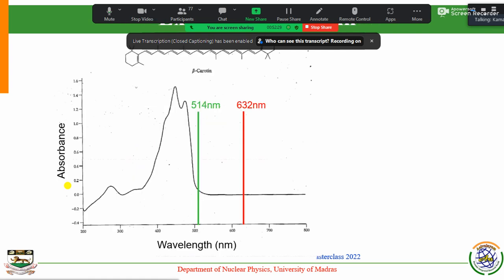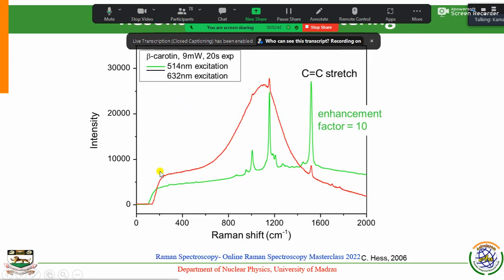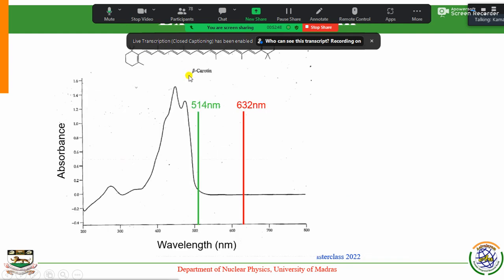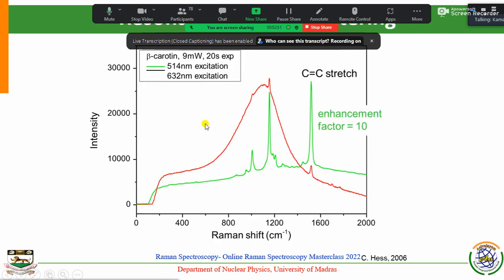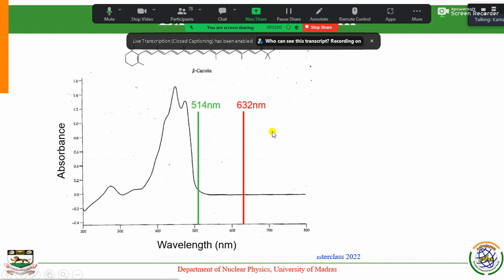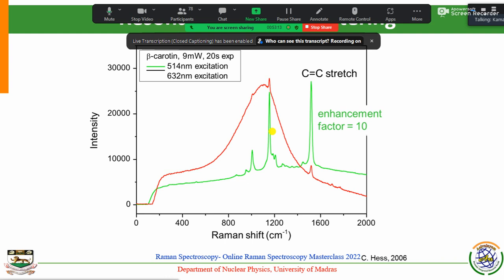For that case you can see this is the absorption of the material. 632 is lesser energy compared to 514. So whether I should give 514 or 632, you can see the result here. If I take 632 nanometer excitation, it gives the broad feature of the system. If I take 514, which is almost near the absorption of that material, it gives a larger number of Raman modes, which means they are clearly visible. So the electrons must be excited in between the electronic states, as well as the laser being almost near the absorption of the system. You will most probably get better Raman modes.